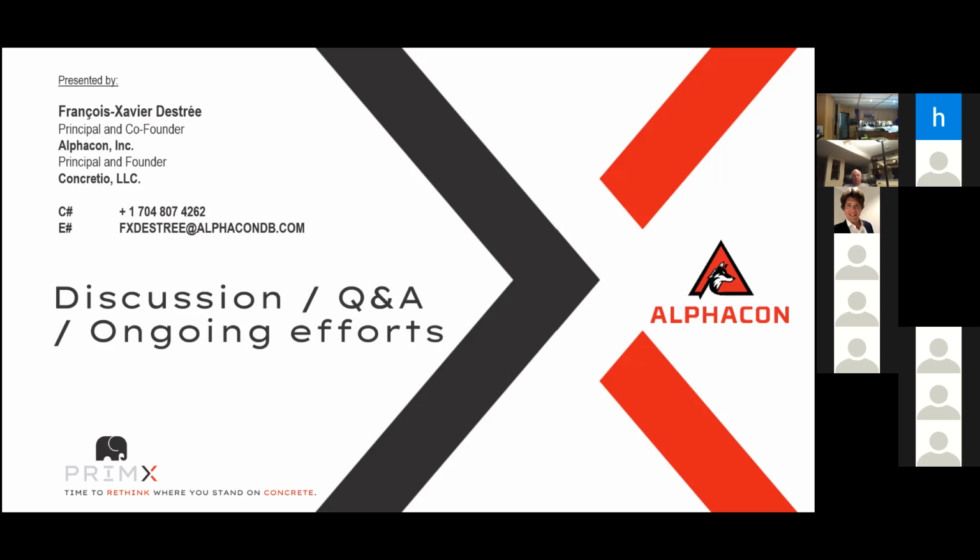Okay, thank you, Francois. Francois, can I just add in that on a project just recently completed, the one that Francois was mentioning, for the wet cure the contractor put down some mats, and I apologize, I can't remember what that exact product was, which retained the water. Basically for the first 14 days, somebody had to be there at least daily, checking to make sure that the moisture content was there, and if not, spray it down with water. So you're using quite a lot of water to maintain that water on the surface. But as I said earlier, there was a mat laid which allowed the water to stay there, and it never dried. It was only after 14 days that those mats were taken off and the surface was allowed to dry.